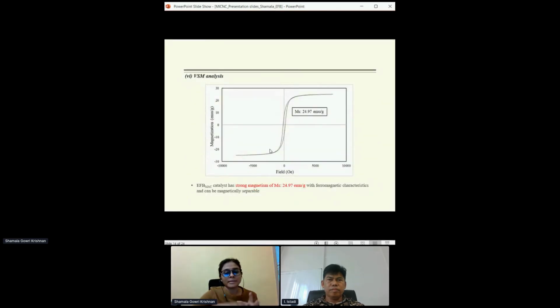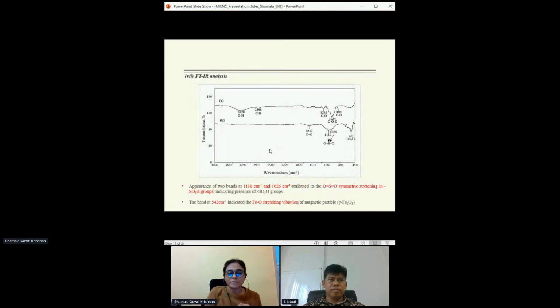And the easy separation of the catalyst can be explained by the presence of strong magnetism in the catalyst with 24.97 EMU per gram. The functional groups in the catalyst were determined by the FTIR analysis, and the existence of two bands at 1110 and 1026 was attributed to the presence of sulfonic group, and the band at 542 indicates the presence of ferric oxide.